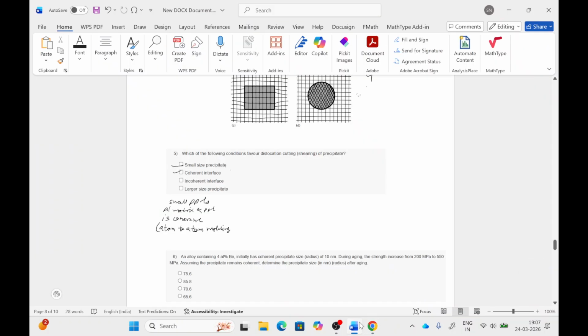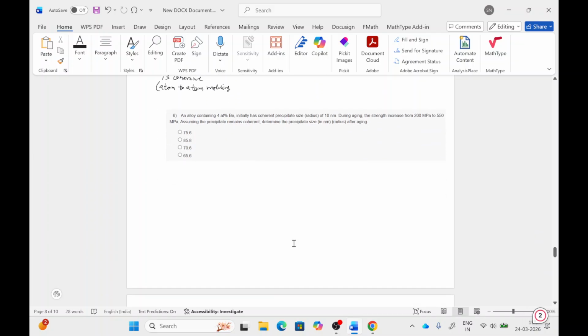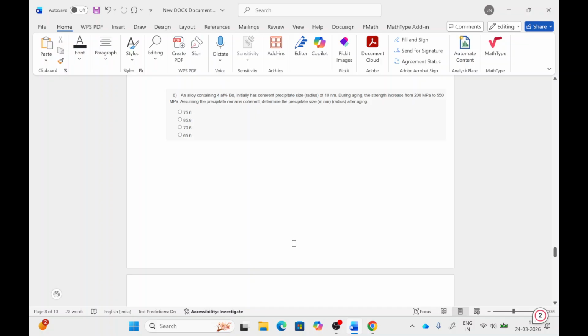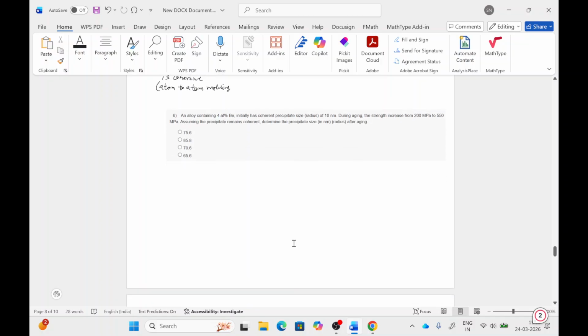Okay, we'll go to the next question. In the sixth question, we have asked: an alloy containing 4 atomic percent of beryllium initially has a coherent precipitate size of 10 nanometer. During aging, the strength increases from 200 MPa to 550 MPa. Assuming the precipitate remains coherent, determine the precipitate size after aging.